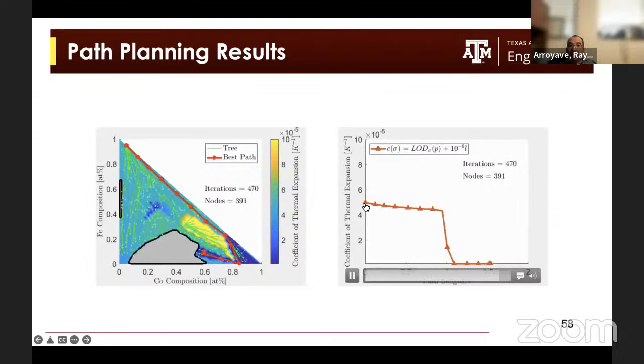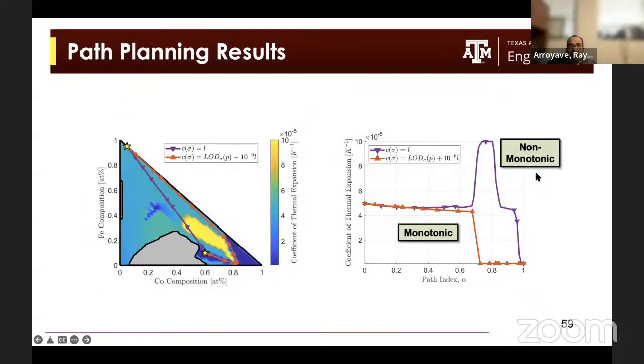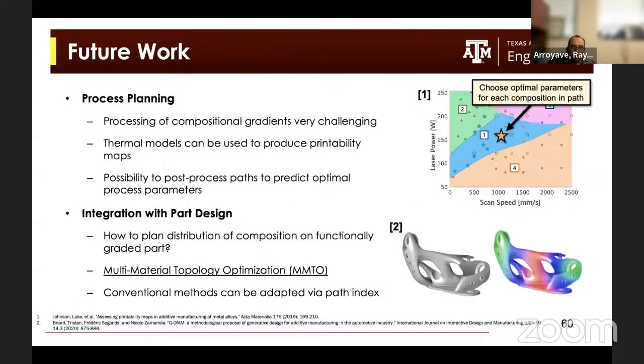And if it's monotonic, that means that just by controlling the deposition rate, we can print any property profile that we may see fit. Okay, this is just an example between the monotonic and non-monotonic path, and clearly this path is likely to have less problems with thermal expansion stress buildup than the non-monotonic case.